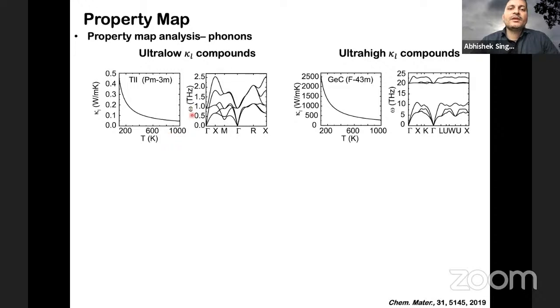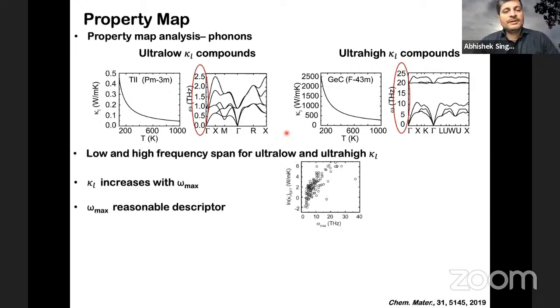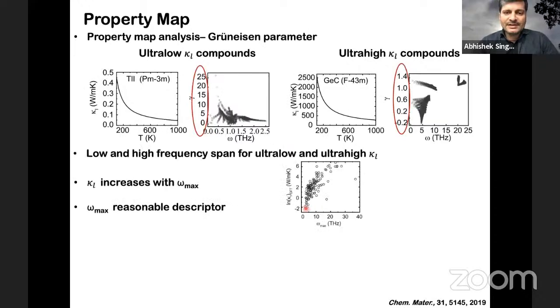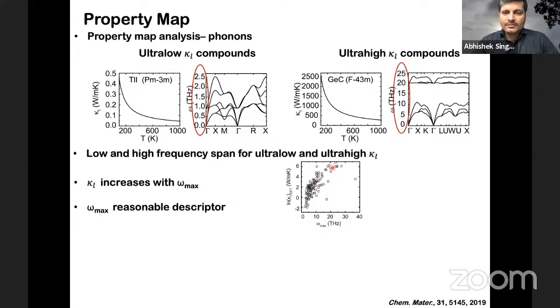For example, omega, the maximum of the phonon frequency, which we call omega max. If this one is low, for example here it's 2.5, the thermal conductivity is also low. If this one is high, for example here it goes to 25 terahertz, then you see the thermal conductivity is very high. So there's almost a one-to-one relationship between them, which we can see here also. You see omega max versus kappa L, and there you can draw a straight line. So there was a correlation between them.